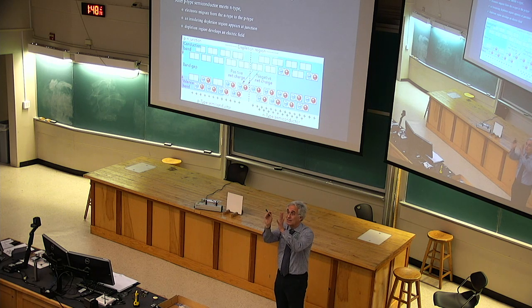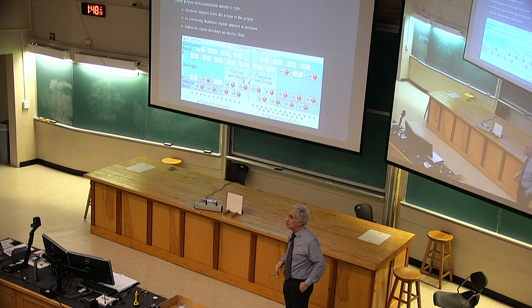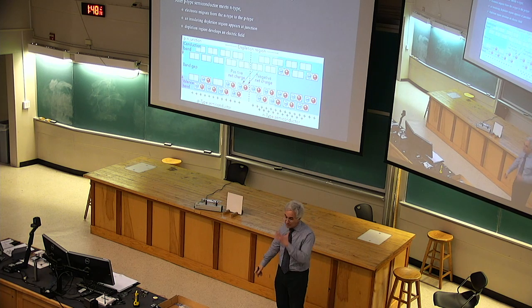It's like a little capacitor. And that building up of charge eventually stops the migration, because eventually it's going to take too much energy to take these electrons out of this side, which is positively charged, and add them to this side, which is negatively charged. There's a repulsion that just says, no, you can't go. So the migration stops, and when it has, look at this central region.